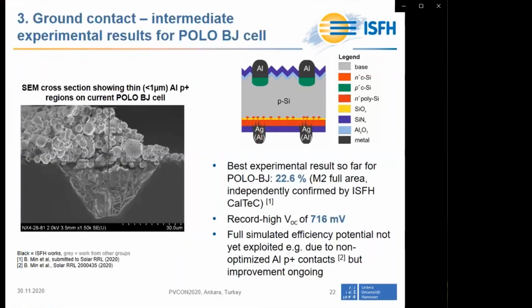To establish the ground contact, I would like to show you here our recent experimental results for industrial POLO back junction cells. We are working on this cell structure for almost 1 year now, and we already achieved an efficiency of 22.6% on full M2 wafers, as confirmed by ISFH CalTeC. In particular, the open circuit voltage is already quite promising. It reaches values of 716 millivolt, which is the highest value reported so far for P-type wafers with aluminum P+ regions. Of course, the simulated efficiency potential is not yet fully exploited, and the major reason for this discrepancy is that the aluminum P+ regions, as shown here in this cross-section SEM image, the bright areas are the P+ regions.